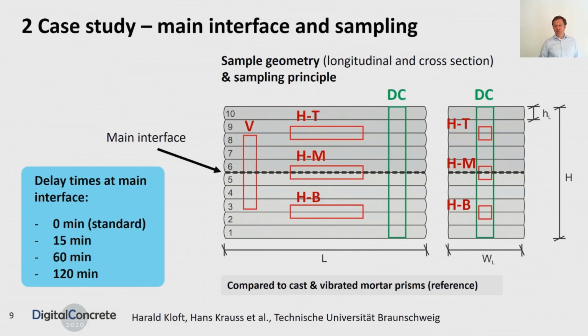Finally, we also took a drilling core in order to analyze the air void distribution by computer tomography. And we compared the two printing methods to cast and vibrated mortar prisms as a reference.